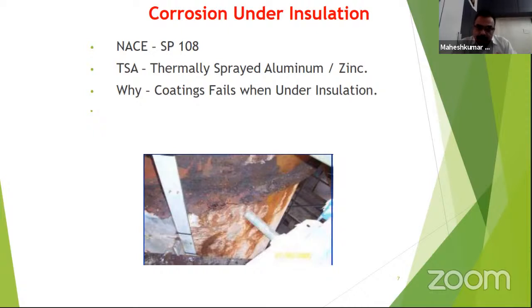I want to remind you of a NACE specification, that is NACE SP 108. This is the specification which is derived for coatings for under insulation and under no insulation areas to be used onto offshore structures. As far as NACE is concerned, they haven't given any material recommendation in any of the specifications, but specifically in NACE SP 108, they have mentioned that for the insulated area, you must go only for TSA, that is thermally sprayed aluminum zinc, to be used under insulation areas. Then why do coatings fail in those areas?